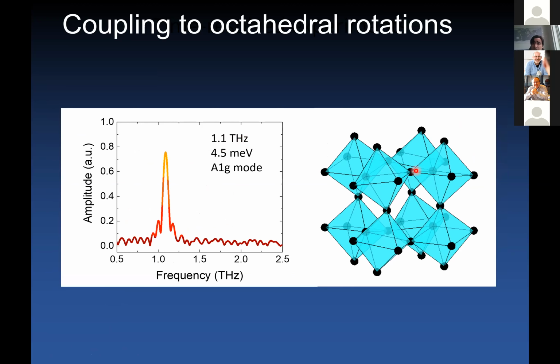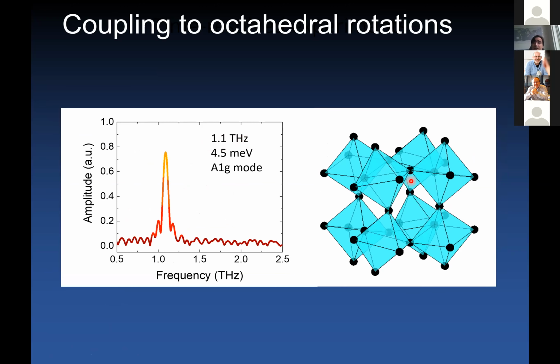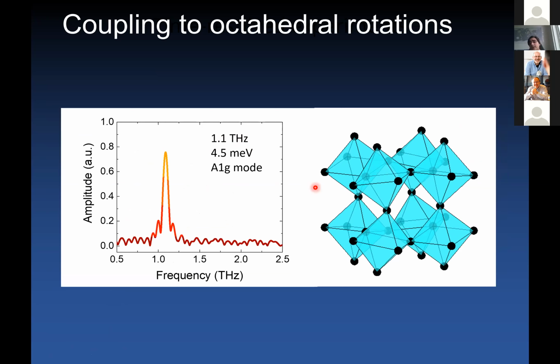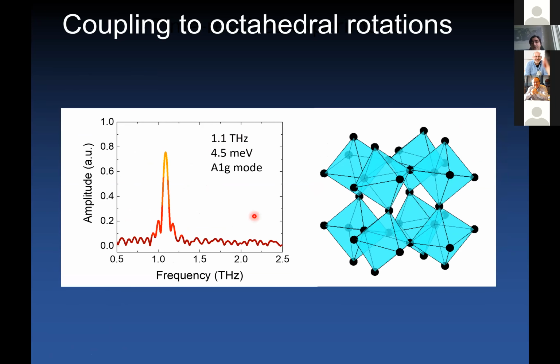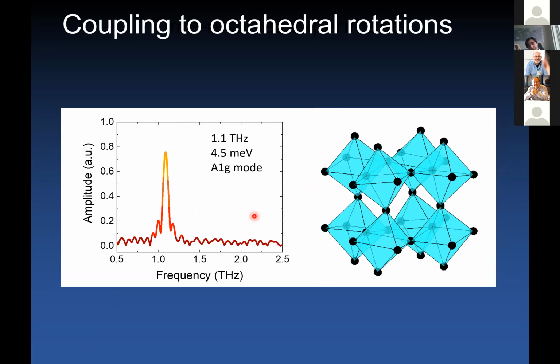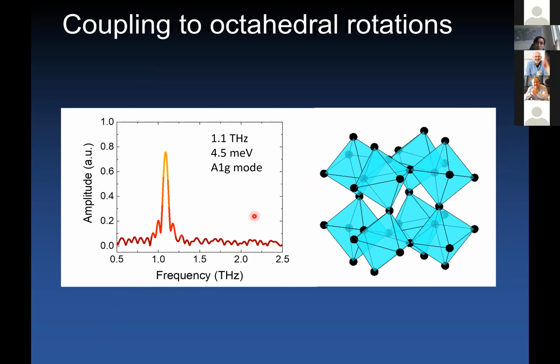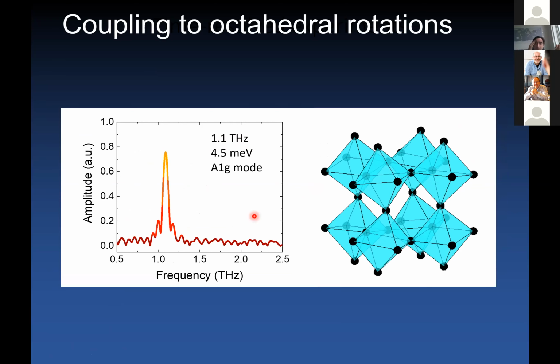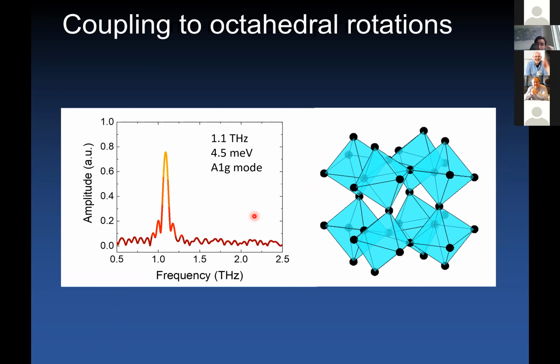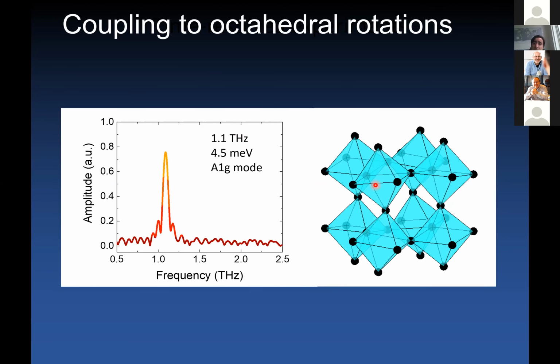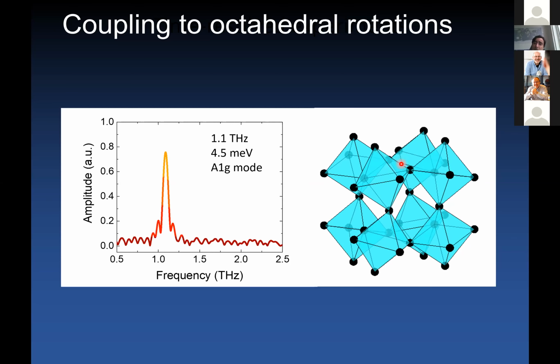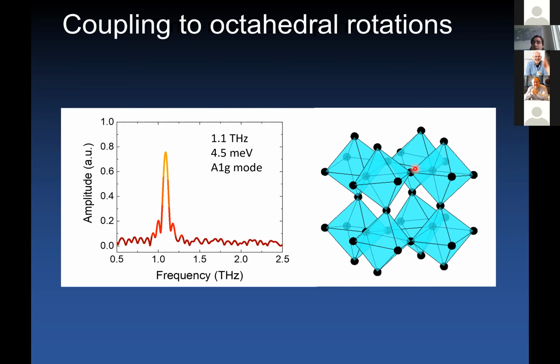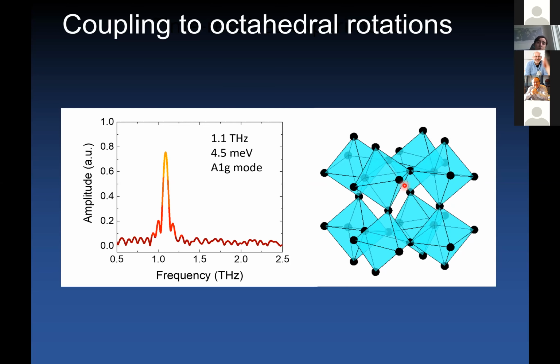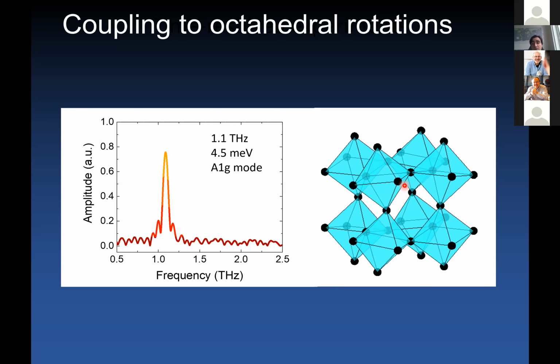So this is an oxygen octahedral rotation mode. So it's a Raman active mode that has been excited through nonlinear coupling between the phonon modes. So by exciting a phonon mode at 20 terahertz, you have induced a rotation at 1.1 terahertz of your oxygen octahedra, through nonlinear phonon-phonon coupling. As I told you before, it's very important to be able to access these oxygen octahedral rotations, because these govern a lot of interesting electronic properties of our materials. So this is what we are aiming to do here, to control on very fast time scales these structural modes of the material and to induce transformation in the electronic properties.